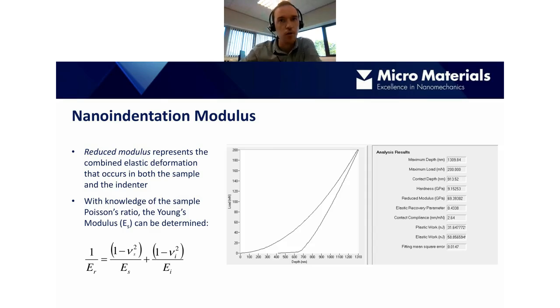So what you can see here is a fused silica indentation. Again, we use this as a reference material. And you can see the reduced modulus is 69.4 gigapascals. And if we convert that to the Young's modulus, that would come out about 72. Okay, so as the reduced modulus, or as the stiffness of the material decreases, then there's very little difference because of the difference in stiffness between the material and the diamond.